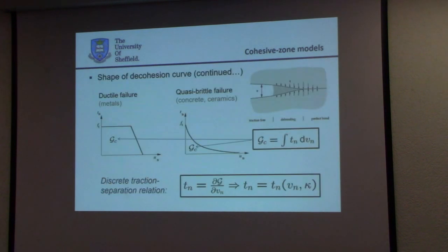In this definition here, you lump all the other inelastic effects in it. So this is why in linear elastic fracture mechanics you better talk about fracture toughness, and in cohesive zone models, you better talk about the fracture energy that is dissipated. It's a fine but indeed important point. And I do admit that the distinction is not properly made often in the literature, and I also have the tendency sometimes to be a bit sloppy there.